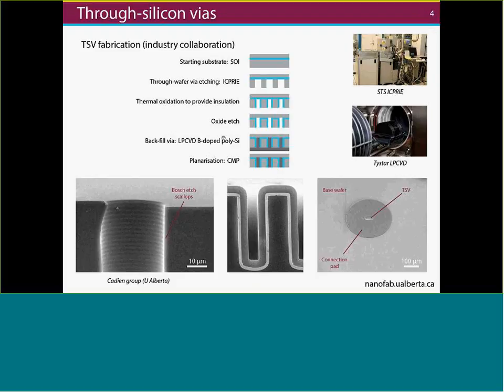Now, I'd just like to point out that CMP, we do not currently have that capability in-house at the NanoFab, but it is available at other FACT labs. So for this process, this is an ICP or RIE tool which is used for some of the deep silicon etching in this project. Then SEM images of various parts. This is an example of the via, and you can see the scallops characteristic of a Bosch etch process. And you can see the handle wafer, the silicon, which has been oxidized to provide insulation, and an incomplete polysilicon fill. So eventually, at the end of this process, this via gets completely filled with the polysilicon.